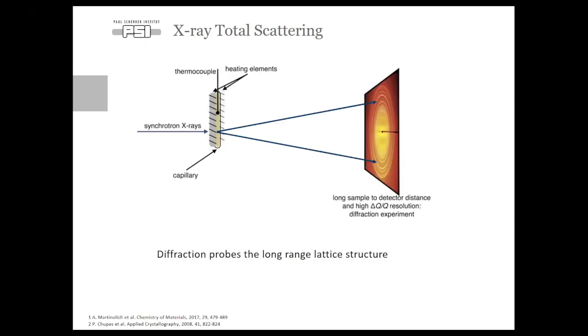Most people will be familiar with X-ray diffraction, where you can use a 2D image plate at a long distance from a sample to collect a very high resolution diffraction pattern and then refine, using Rietveld refinement methods, the long range order, so the Bragg diffraction, and, as such, the crystal lattice of the material.